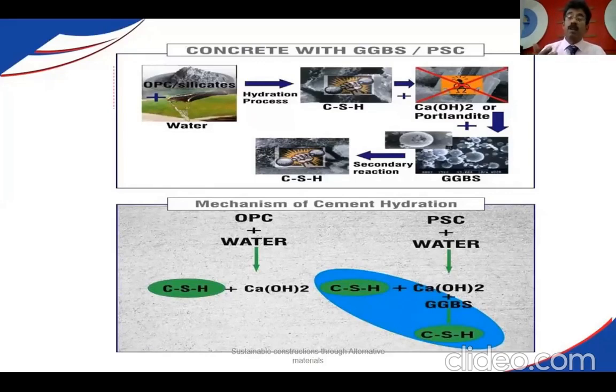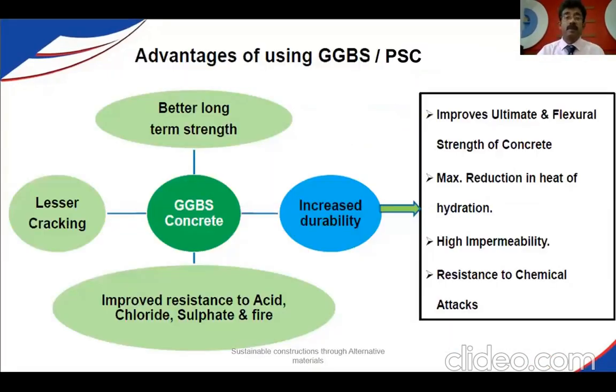So it's both hydraulic and also pozzolanic in nature. This is the reaction. So this double reaction will take place along with the cement and water. When it has reactions and additional products are liberated, the hydration products, you are going to have better long-term strength, increased durability, lesser cracking, because you are removing the C3S or C2S content in the initial from the cement. So lesser cracking will happen, and also resistance to acid and chloride attack.